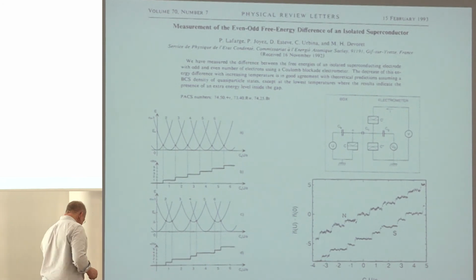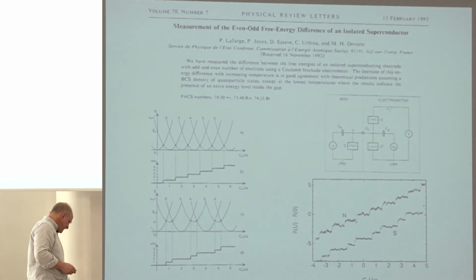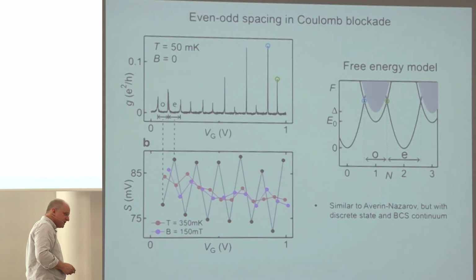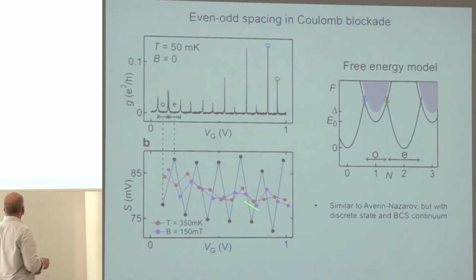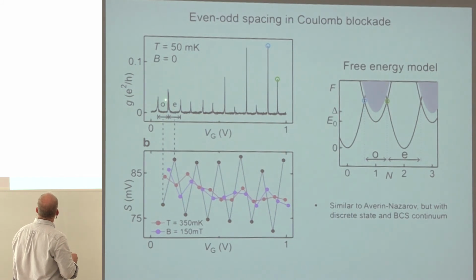And that indicated, as this experiment pointed out, that every last electron was being paired in the superconductor. We see a similar thing in the zero bias case, where it's a little bit hard to see from here, but here are the Coulomb blockade peaks, and they indeed go little step, big step, little step, big step, little step, big step. And those little step, big step can be quenched either by turning up the temperature or by turning up the magnetic field.